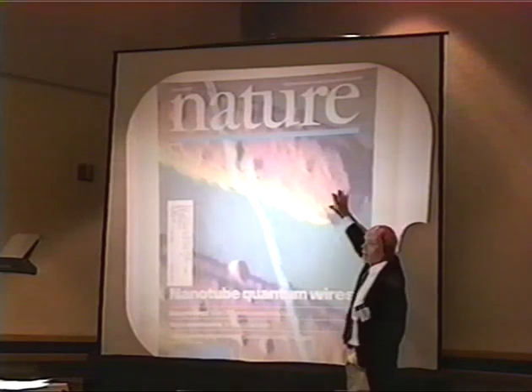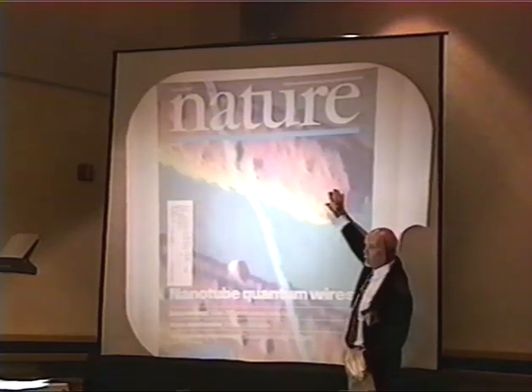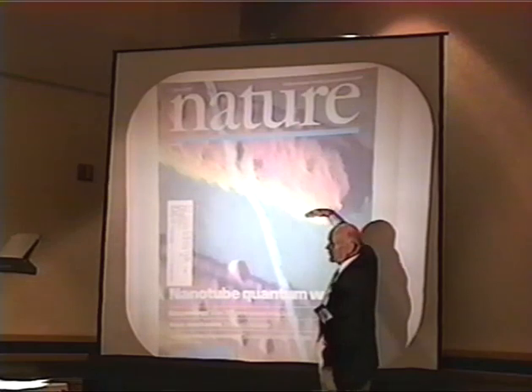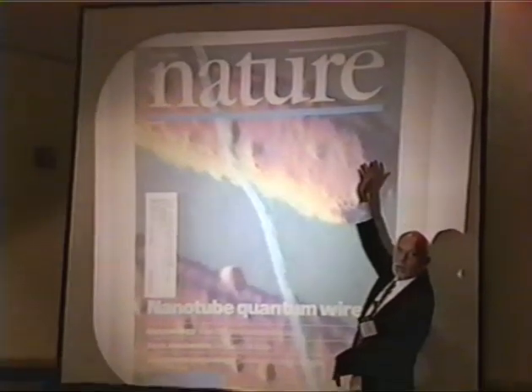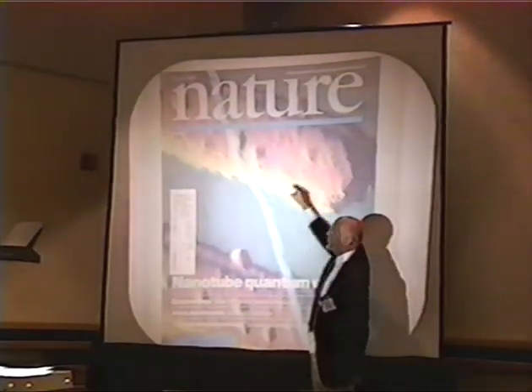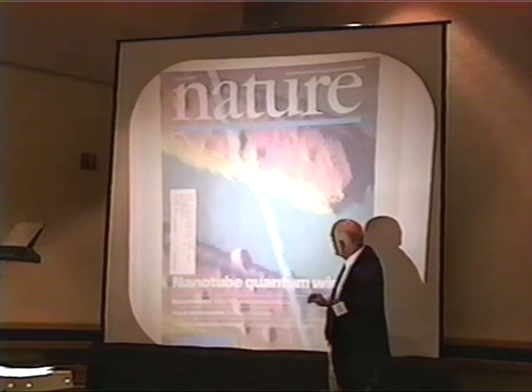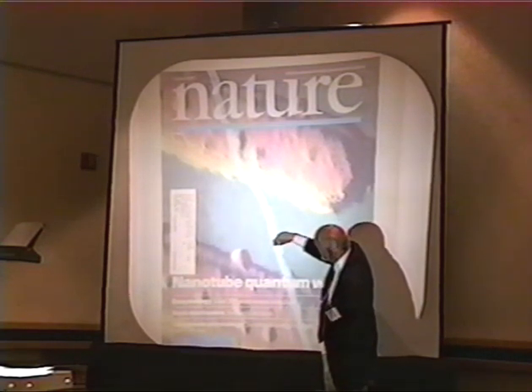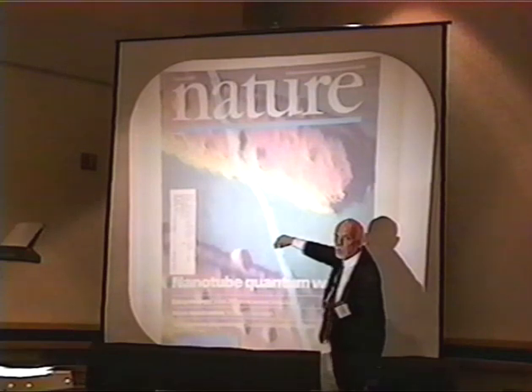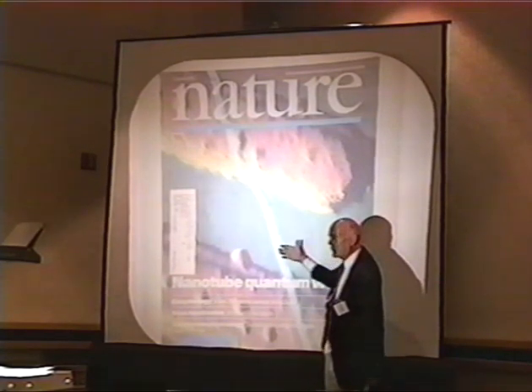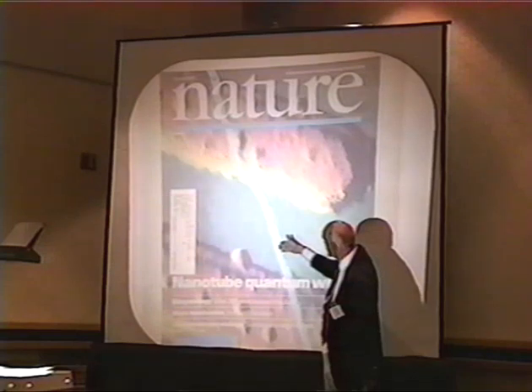But this is actually very high technology. This is microlithography done at scale. This is only, what, about 100 nanometers across here. And this is on silicon, I believe, isn't it? Silicon oxide. And so this is the old yucky technology of microelectronics. And then here, casually draped across it, is the new technology. This is the way to make a wire, not this cruddy old stuff. This thing is a single molecule. It's actually considerably thinner than seen here. This is extra fattened by the tip that the Dekker crew was using.